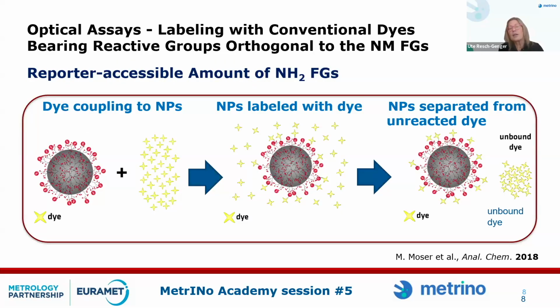So how do such assays work? When you have dye coupling to the nanoparticle, you add your dye, then you label your particle with the dye, wash away the excess dye, and then measure the particle and the dye. The problem here is you need to have several washing steps. Then the question is, do you have unspecific adsorption? And what is often recommended here is to go for a mass balance. You know how much you add. Then measure the dye in the supernatant and measure the dye on the particle.